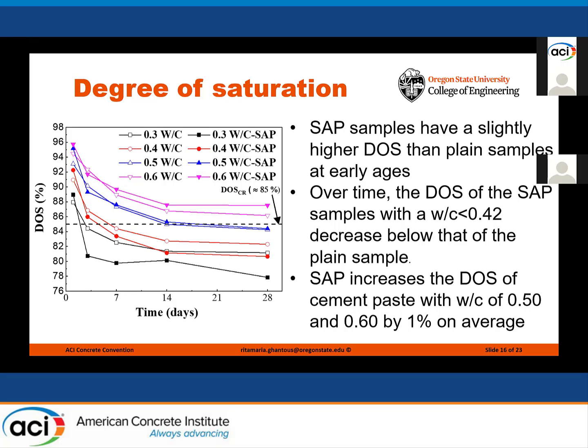So we have the degree of saturation on the y-axis versus the curing time on the x-axis. The black and red are 0.3 and 0.4 water to cement ratio respectively. Blue and pink are 0.5 and 0.6. So we can see that the degree of saturation of sample with low water to cement ratio is lower compared to the other one with high water to cement ratio. And then the dashed line here is the critical degree of saturation, which is the value that define when freeze-thaw damage will start. So you can see that samples with low water to cement ratio drop below this value earlier than samples with high water to cement ratio, which means that samples with low water to cement ratio will better resist freeze-thaw damage compared to samples with high water to cement ratio.